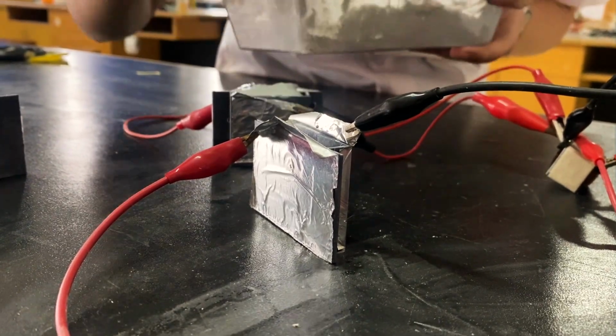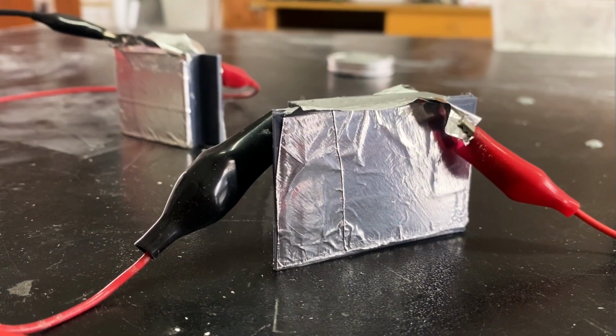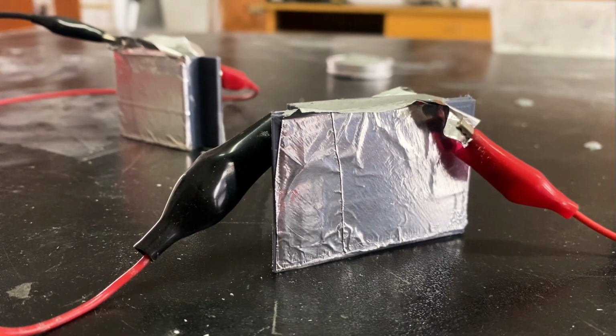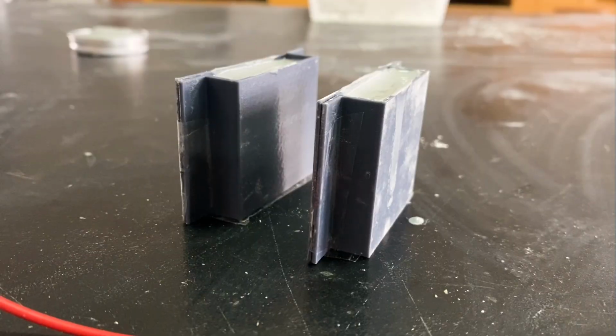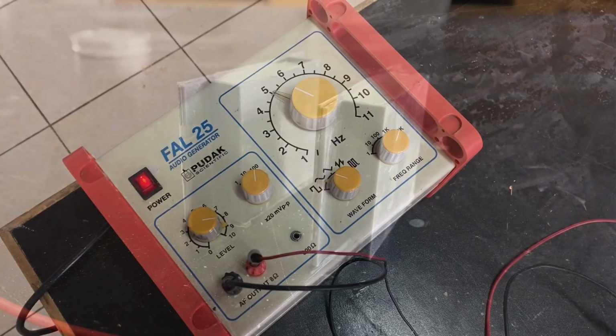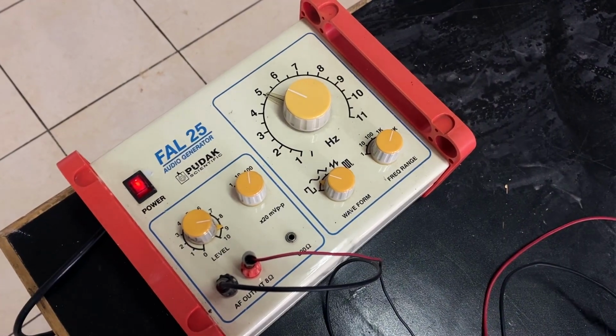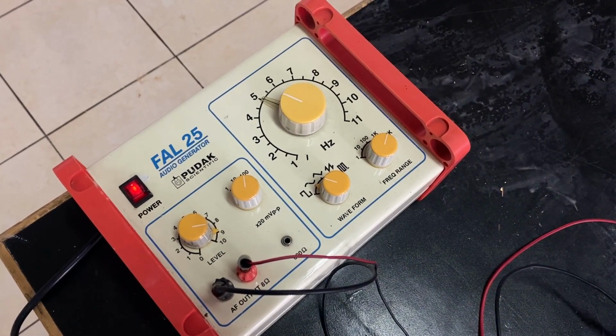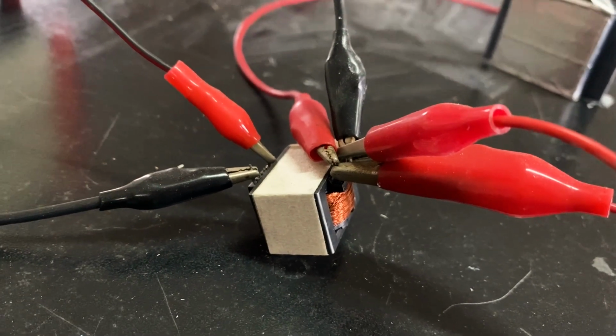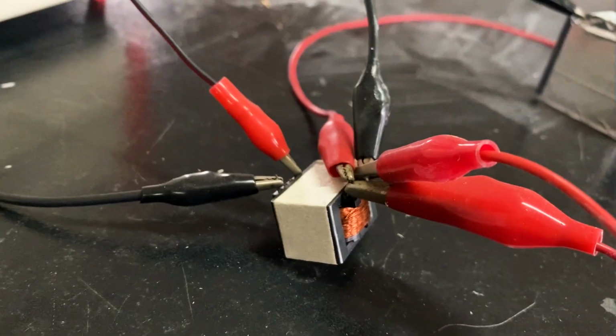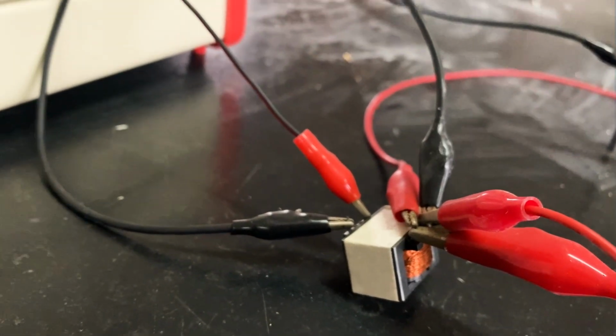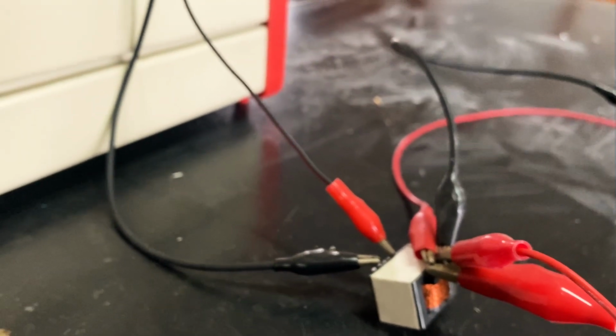it has hardened. Each combination of carbon gypsum is made with 2 different treatments. One is given an electric field for 1 day and the other is not. To generate the electric field, a voltage up to 190 volts and a frequency of 50 kHz was applied from a signal generator. Using a step-up electrical transformer, the voltage is sourced from a 10-volt source. The ratio of the primary coil to the secondary coil in the transformer is 1 to 18.5.